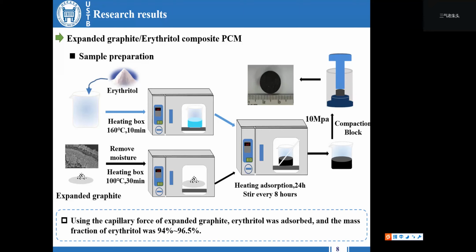Firstly, the erythritol was heated at 160 degrees for 10 minutes to melt the phase-changing material. The expanded graphite was then heated at 100 degrees for 30 minutes to remove moisture. Then the two were mixed, heated, and adsorbed at 116 degrees for 24 hours, with stirring every 8 hours.